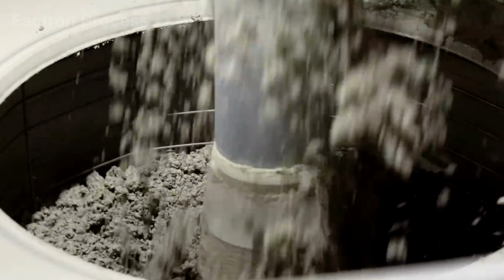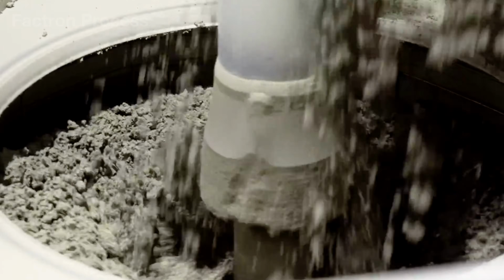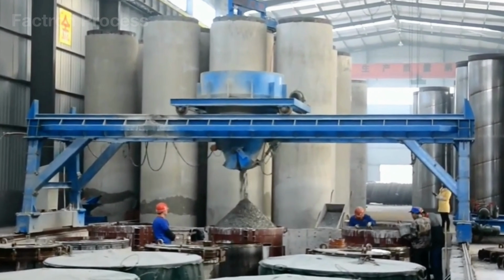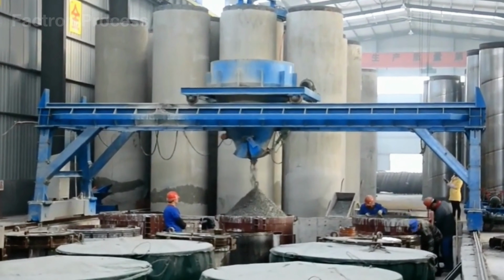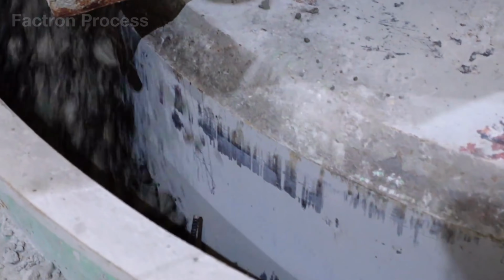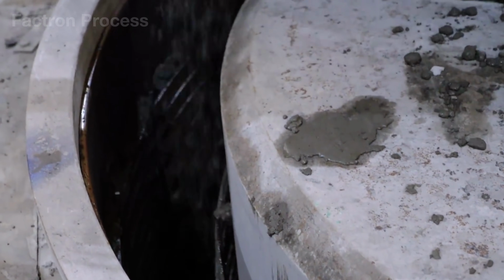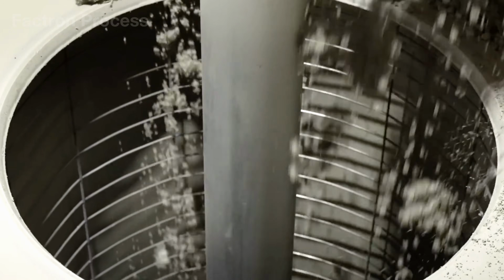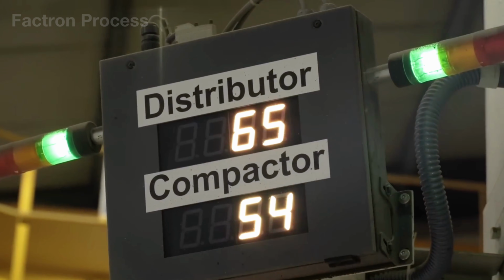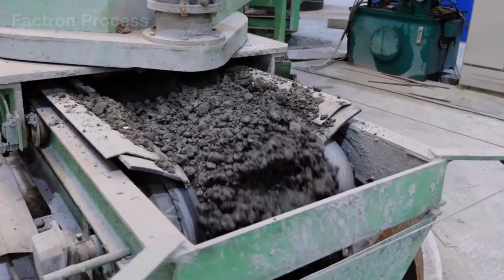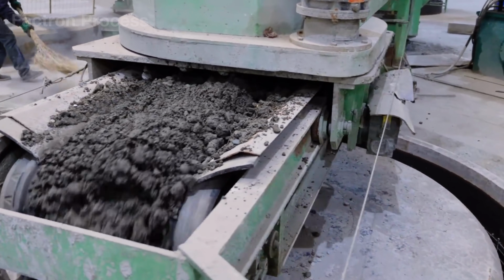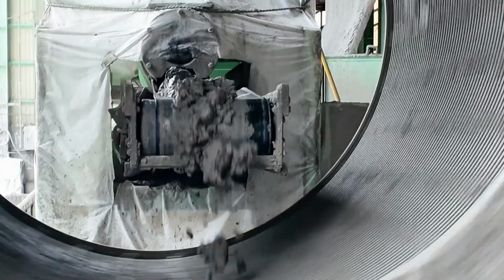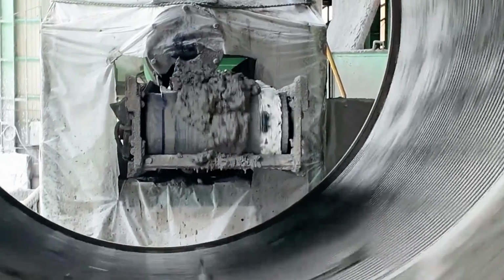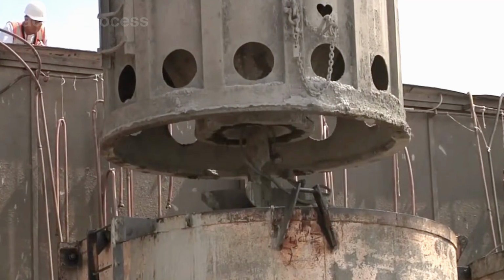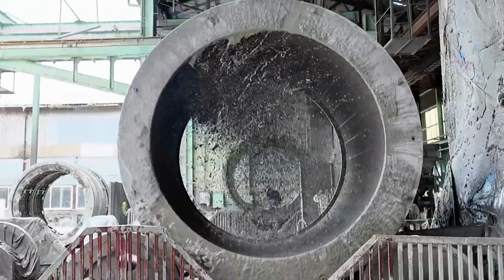As more concrete continues to fall, the head slowly rises through the full height of the product, which can reach around 12 feet on some production lines. With every rotation, the stone particles are pressed closer together, trapped air is forced out, and the inner surface of the pipe becomes progressively smoother. The outer mold defines the outside shape, while the packer head determines the inner diameter. On larger machines, this process can produce pipes up to 84 inches wide.